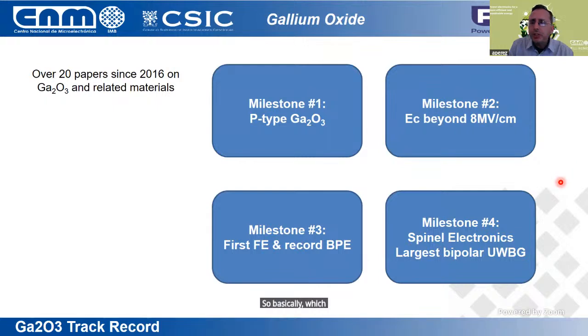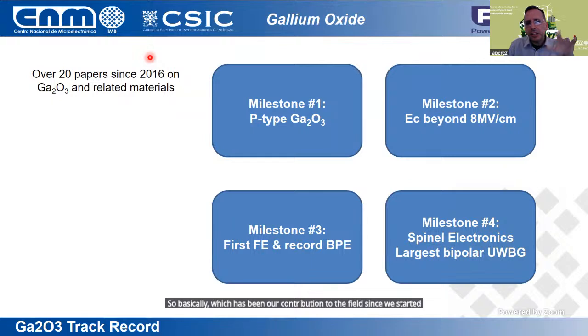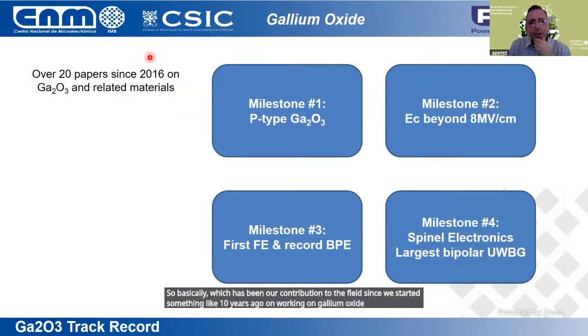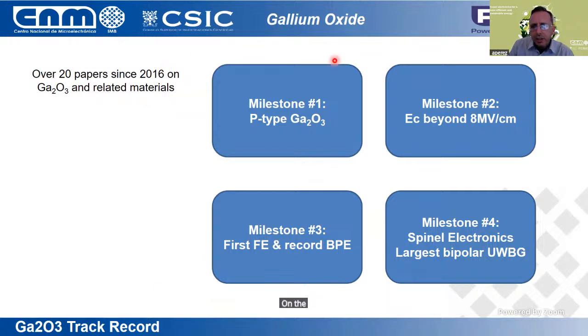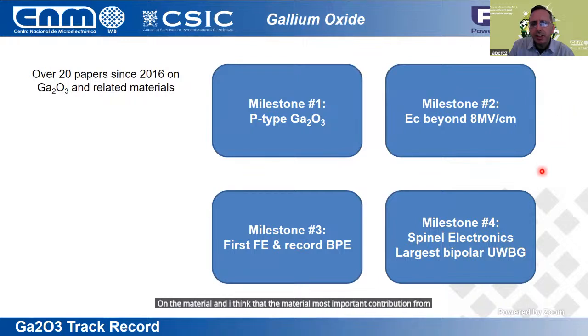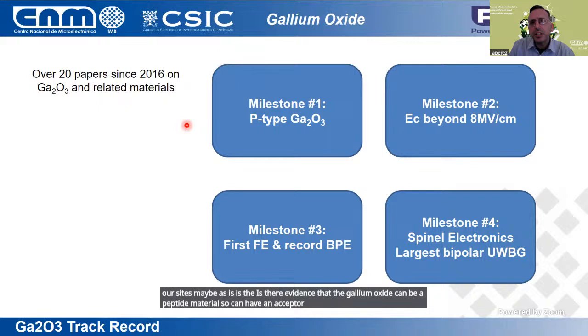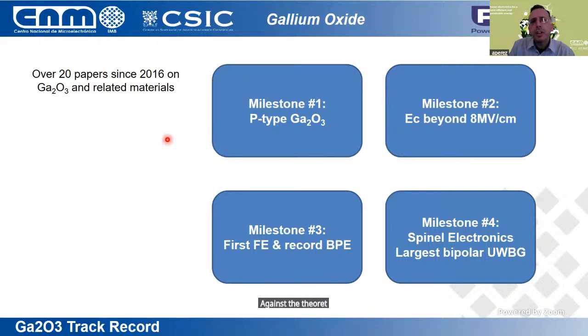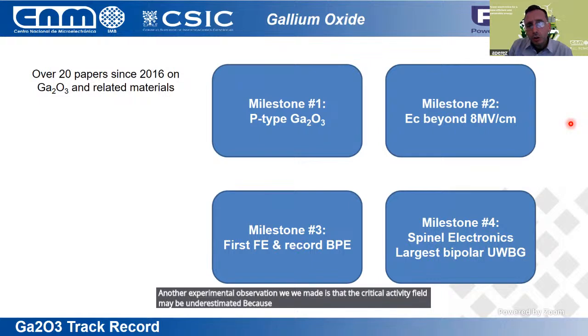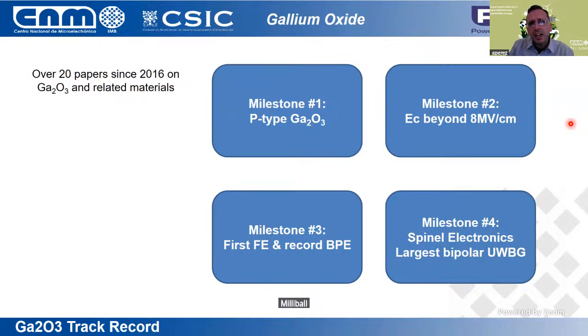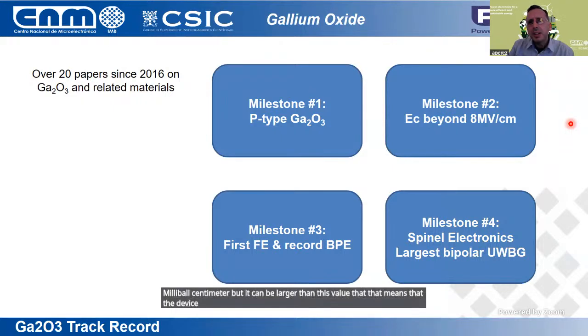So basically, which has been our contribution to the field since we started something like 10 years ago working on gallium oxide. We have published some 20 papers or more on the material. And I think the most important contribution from our side is maybe the evidence that gallium oxide can be a p-type material, so it can have an acceptor nature, but that was against the theoretical approaches and results at the time. Another experimental observation we made is that the critical electric field may be underestimated because it is considered a value of 8 megavolts per centimeter, but it can be larger than this value. That means that the device can work even better than we expect.